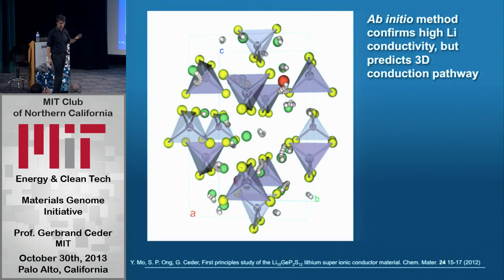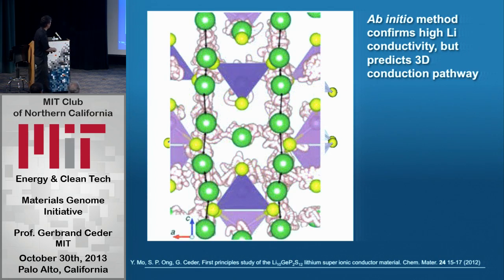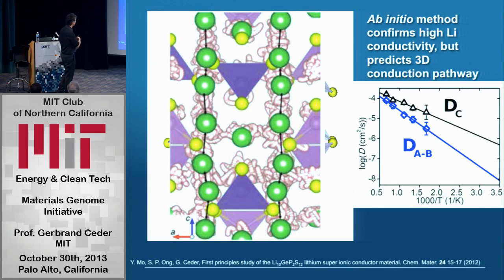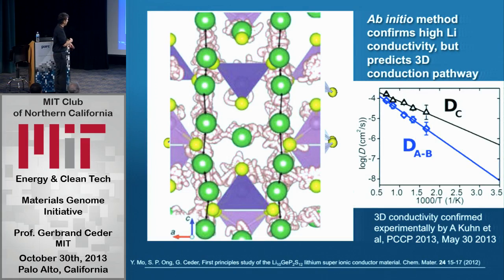that it's a 3-dimensional conductor. And this is really important because a 1-dimensional conductor would have never worked in real life. It's a 3-dimensional conductor, so it conducts in 3 directions, which is really important. You can see that from the simulation. And that's now confirmed by experiments, just a few months ago.